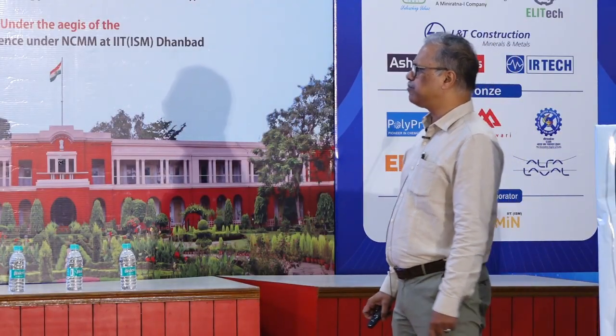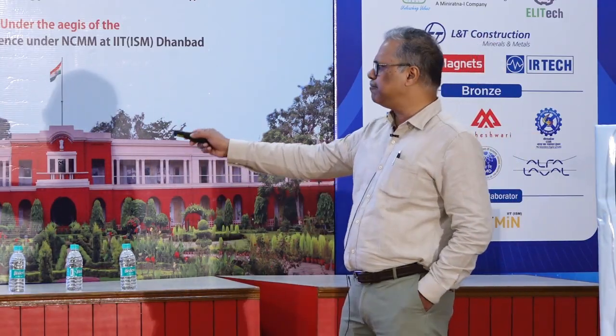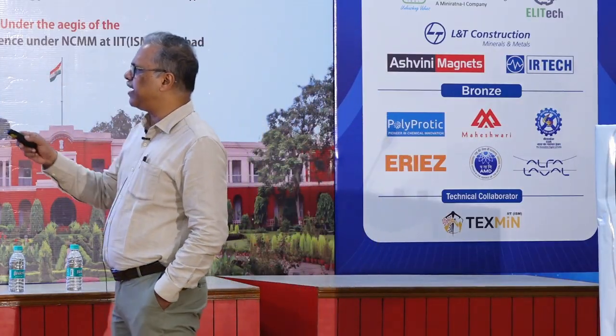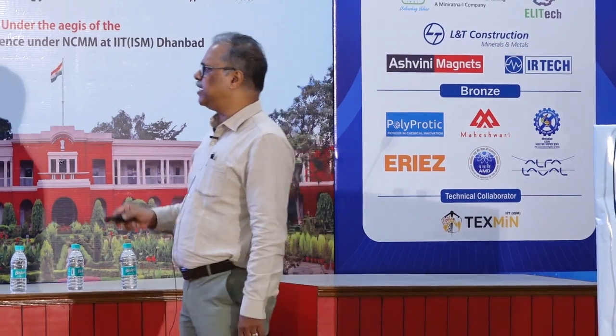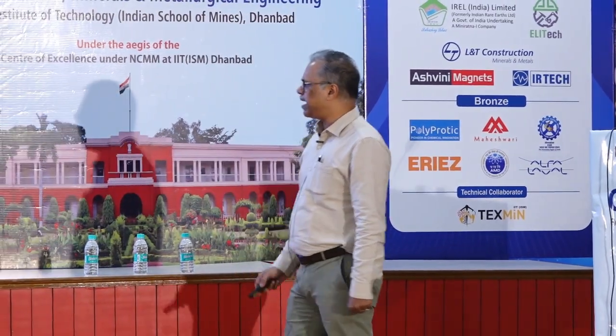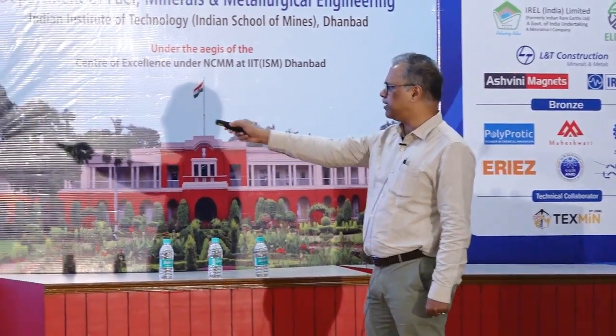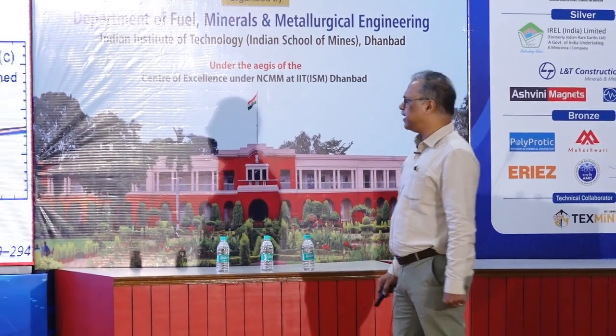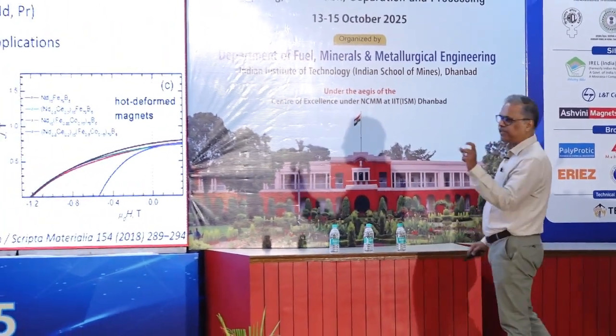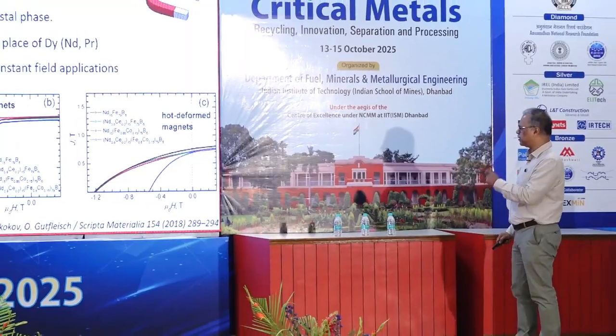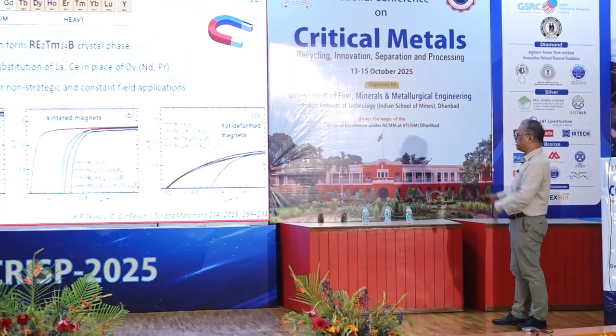Now, in NdFeB there are other rare earths also, like cerium and cobalt. This one is for single crystals, and the red one is NdFeB without any additions. With additions, the property is reduced a little bit, not a drastic decrease. When you come to the sintered magnets, the red one is far ahead, whereas for the other materials, once we replace Nd with Ce as well as cobalt, you can find it gets shifted to the other side.